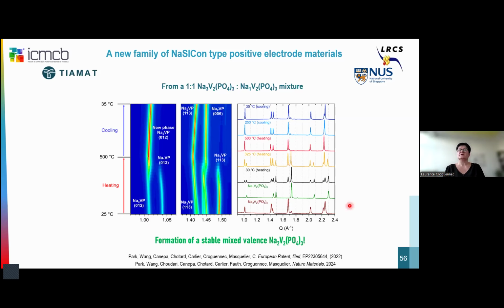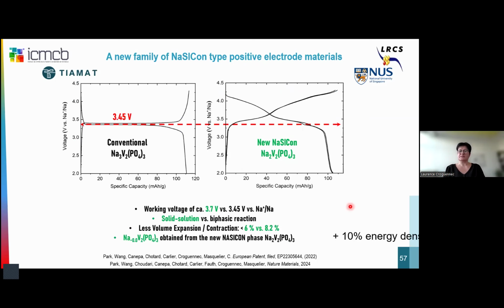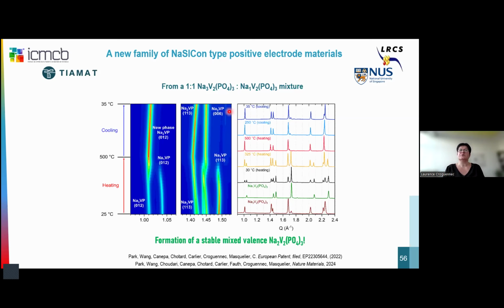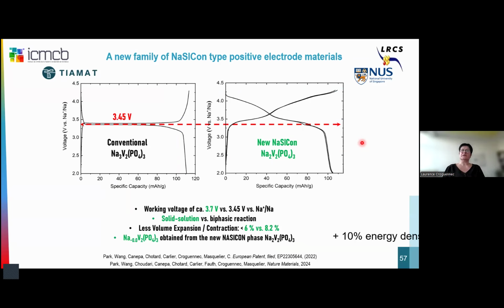And we did this for different compositions and mixtures between Na3 and Na1, and we were able to stabilize like this a series of materials. Why are these materials interesting? In fact, on the left, you can see here the conventional electrochemical signature of NVP, Na3V2(PO4)3, a flat plateau at 3.45 volts, and you can see here the signature of the new NaSICon material Na2V2(PO4)3, a much higher working voltage at 3.7 volts.